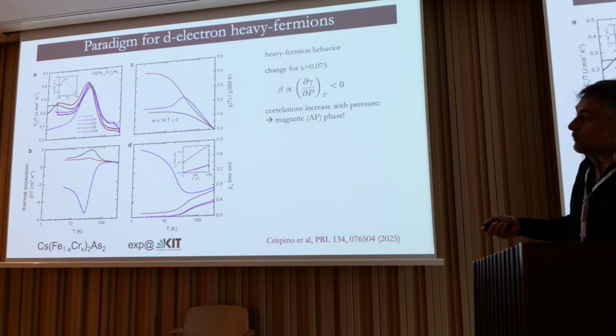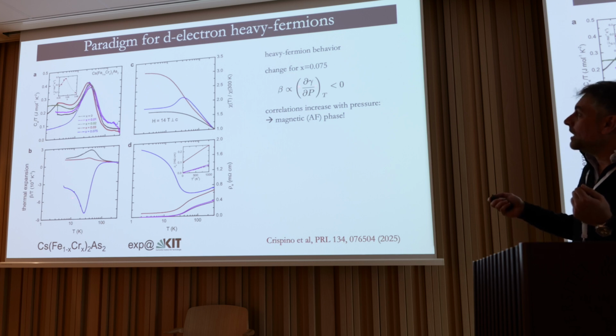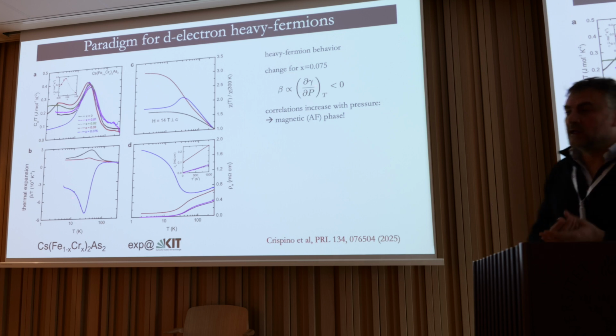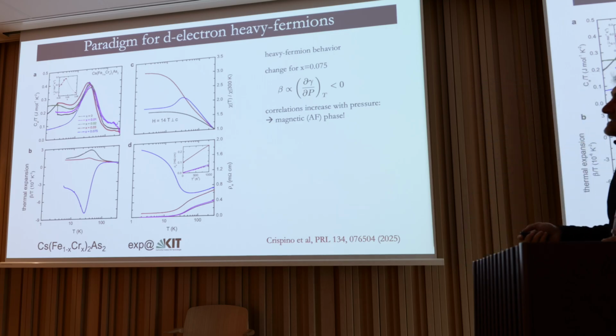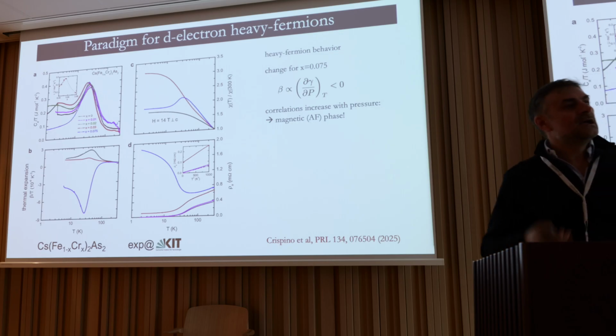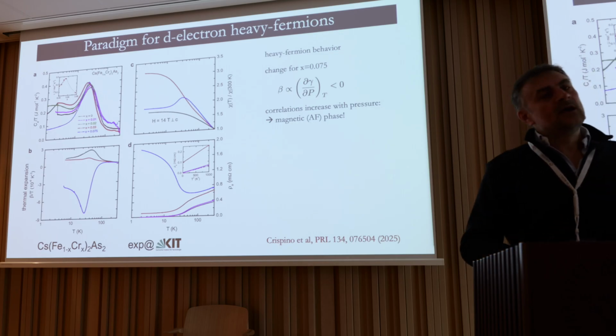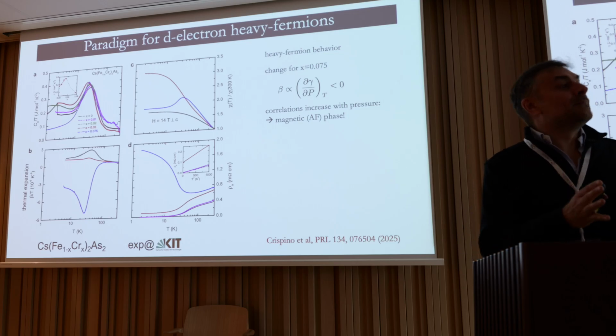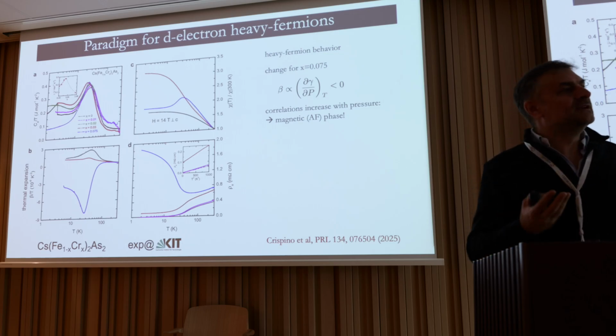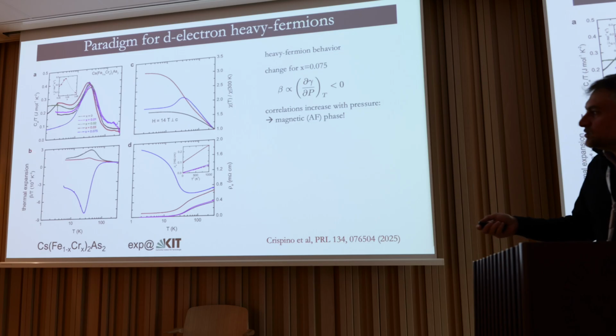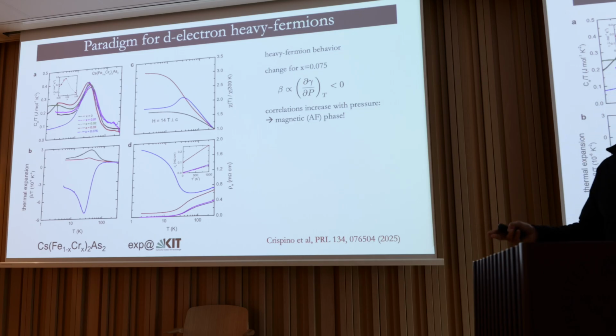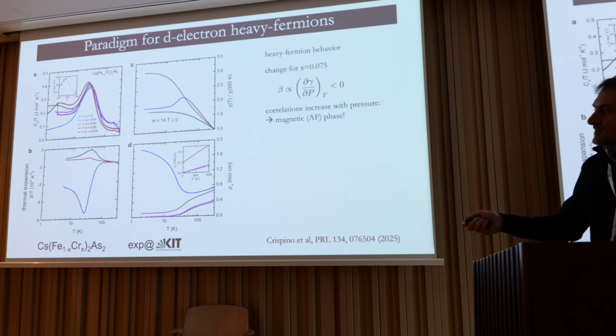So what happens here? Well, this thermal expansion coefficient tells us one thing. There is a thermodynamic Maxwell relation that tells you that if the thermal expansion coefficient is negative, this means correlations are increased by applying pressure, which is the opposite of what we usually have. The usual behavior in heavy fermions that we understand is if you apply pressure, you reduce the correlations, and this is the positive thermal expansion.